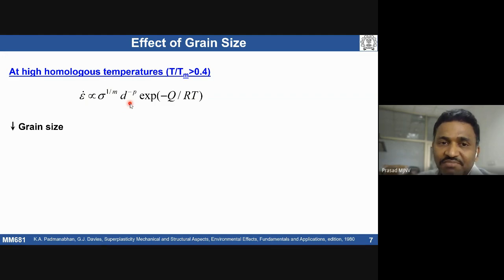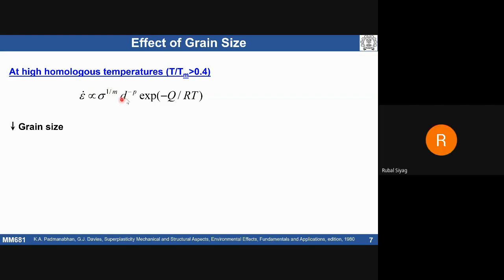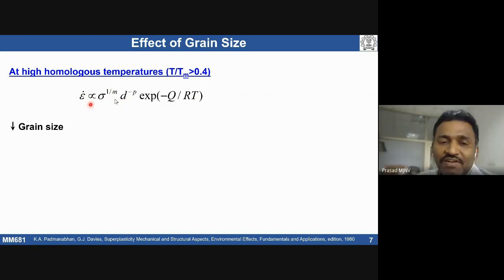According to this equation, if you refine the grain size, what are the beneficial things we can see? For high strain rate, what can one expect? The finer the grain size, the higher the strain rate. That's one thing. Anything else? Because I'm only refining grain size, at a particular strain rate, if you deform the material, is your stress requirement going to increase or decrease with refining grain size?